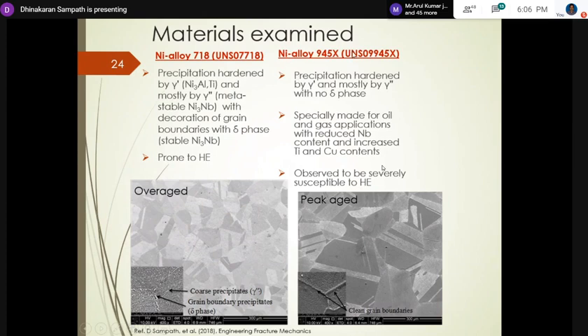And we have this new alloy, which is again precipitation hardened using gamma prime and gamma double prime, but no delta phase, because they found that that's detrimental. So they tried to design it in a way that it doesn't have delta phase. That's why they reduced niobium, which is what forms delta phase. And this alloy's microstructure is peak aged.